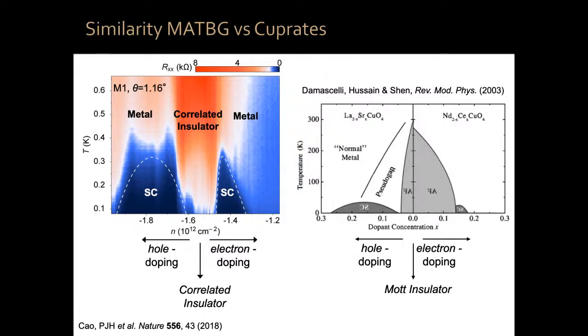At 0 doping concentration, which means 1 electron per copper atom, as I said before, you have a Mott insulator state. You add holes, and you have a big superconducting dome. You add electrons, and you have another superconducting dome. Now, here we have 2 holes per Moire unit cell, a correlated insulator state. You add holes, and you have a superconducting dome. You add electrons, and you have another superconducting dome. Now, there are some similarities and also many differences between these 2 pictures.